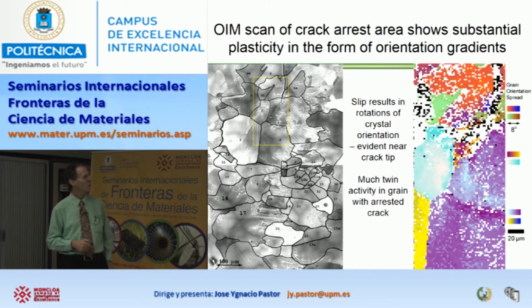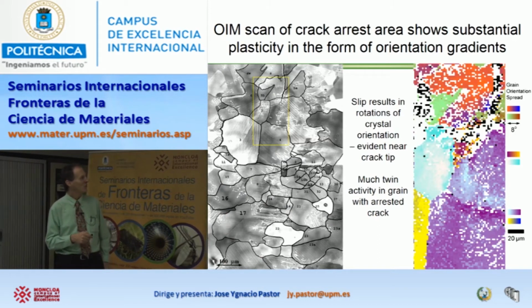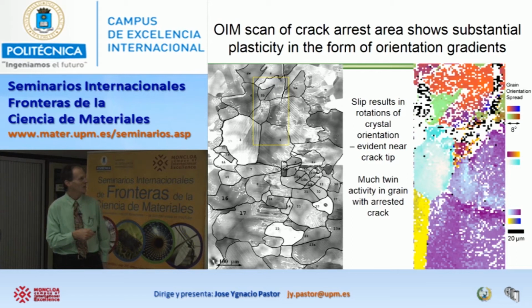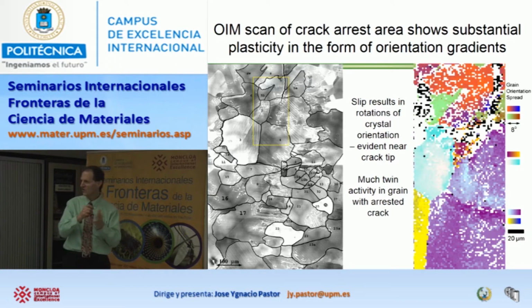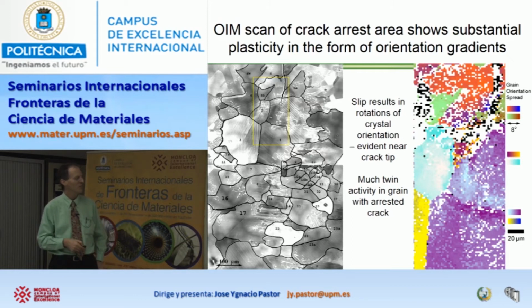Well, that's good. The question is, can we use this in a predictive way? For example, here's a crack in a polycrystal of the same material, titanium aluminide, that was arrested. It came to a halt in a particular grain right here where there's a lot of twinning activity. You can see these lines. And furthermore, if we look in this particular pair of grains, using orientation imaging microscopy, we can see that there's orientation gradients. The color changes a little bit from place to place. That basically means that the crystal orientation has changed. And basically, crystal orientations change when slip is occurring. More slip, more of an orientation change. And it's not the same change everywhere.